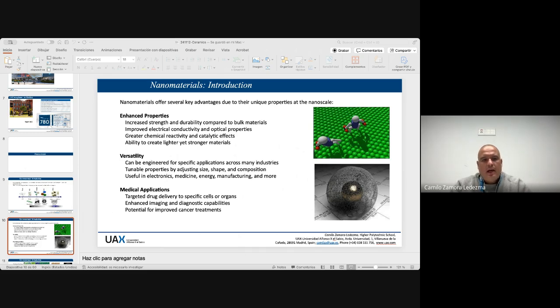First, as I tried to explain at the beginning, we are capable of producing the powder. This powder is transformed into a ceramic via SPS. And then we need to take this material, rectify it, cut it, put it into a resin and polish it in order to perform all the characterization, overall the mechanical characterization.